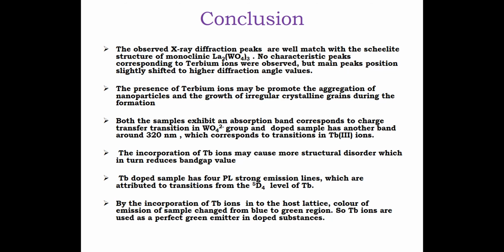Due to the presence of terbium ions in the lattice, the color of emission of the sample changed from blue to the green region. So the terbium ions can be used as a perfect green emitter in the doped substance, and the terbium doped lanthanum tungstate nanoparticle synthesized is suitable for UV light excited LED application.